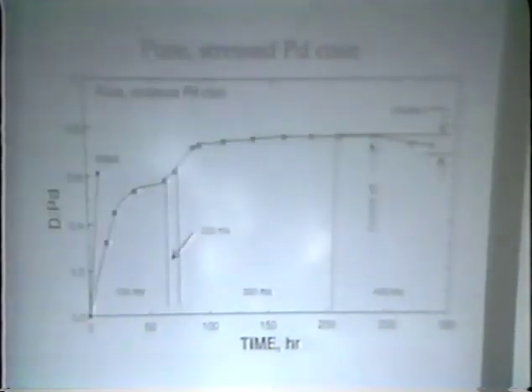Now, not shown on this history, over the last couple of days, we raised the charging current quite substantially, and the level did go up above. It went up to about 0.81 or 0.82. We went up to a total current of 1.5 amperes. Now, I should point out that these are total currents. The area of the sample is about 6 square centimeters, so divide it by 6. I'll let you do the math. But it was a substantial increase over 400 milliamps.